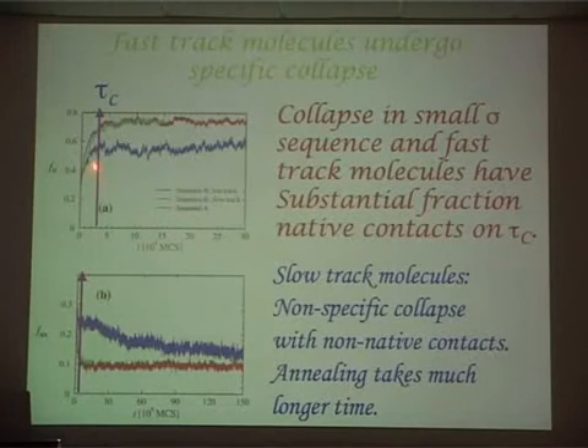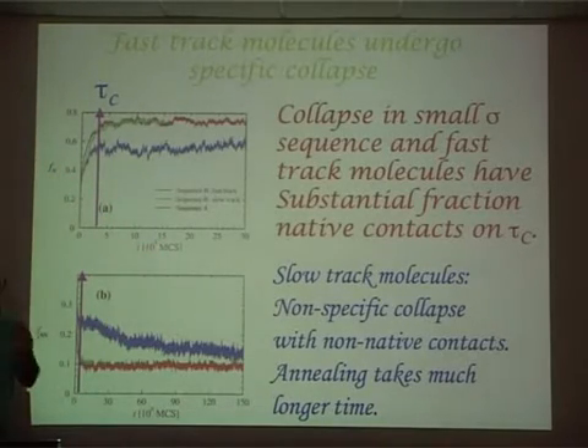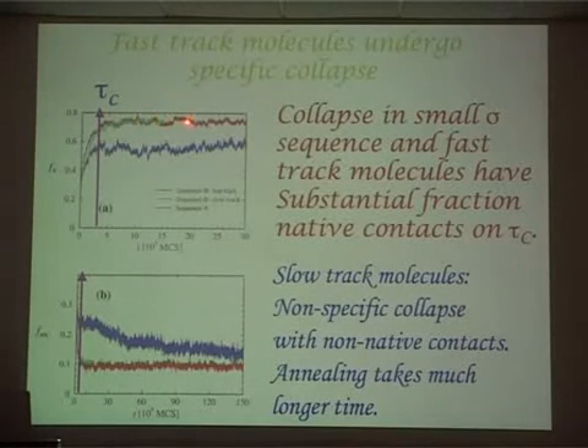So if I look at the native interactions, that's what N here means, as a function of time, that means I'm only monitoring the formation of interactions present in the folded state as a function of time. Again, you see that the green and the red, one of them corresponds to sequence A, only fast track molecules. This is fast track molecules of sequence B. They behave in exactly the same way. The native state is gained very rapidly.